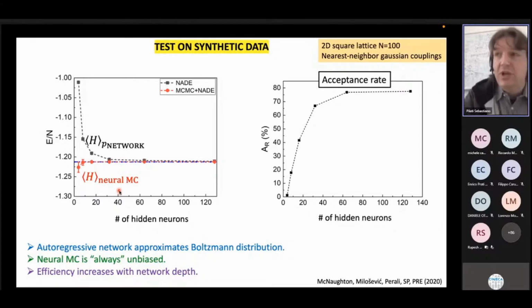But more importantly, the expectation value over the neural Monte Carlo simulation is always unbiased. So you don't need to exactly approximate the Boltzmann distribution. The Monte Carlo simulation is always exact. It might be more or less efficient, so you might get larger or smaller statistical error bars, but in principle, your result is unbiased. And here on the right, you see that indeed the acceptance rate increases when your neural network becomes deeper, and so it can approximate the Boltzmann distribution more accurately, and so you get a more efficient simulation.